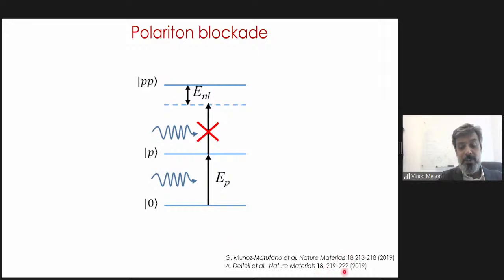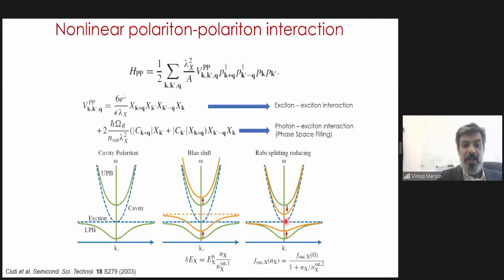Three years ago now, there were these two papers where they showed that when they do a G2 or anti-bunching experiment, they showed a small anti-bunching, essentially indicating that you can get correlations in this system. So we've been after this, and we are primarily driven by the idea that in these 2D materials, we might be able to see this.